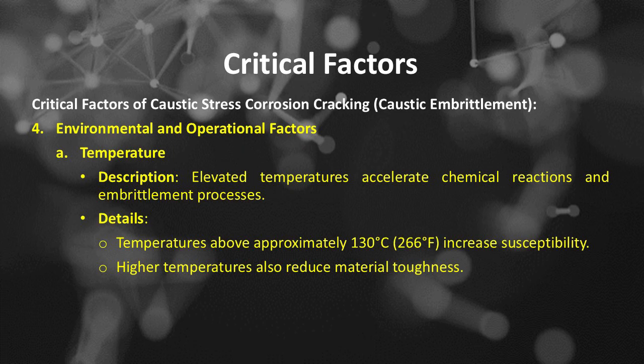Critical factors. Number 4 is environmental and operational factors, which includes temperature. Elevated temperatures accelerate chemical reactions and embrittlement processes. Temperatures above approximately 130 degrees Celsius or 266 degrees Fahrenheit increase susceptibility. Higher temperatures also reduce material toughness.